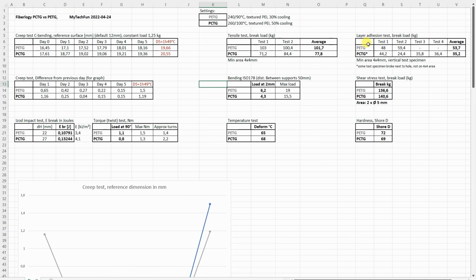Maybe one more thing I want to mention here with the numbers, that's this. So this is the layer adhesion test with test specimens printed in vertical position. And first I got very different results, and one of the test specimens didn't even break on the smaller cross-section area. So I reprinted these test objects in vertical position, and I got these 2 numbers. And basically this is the average value from the 4 test objects.